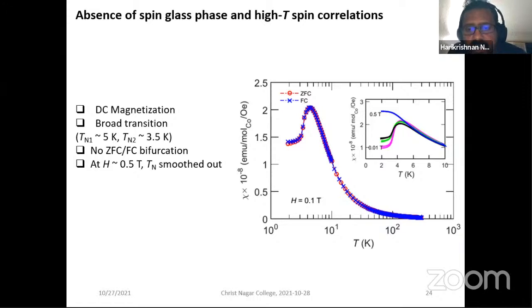Once you measure that, we see a very broad peak below 10 Kelvin. And then with the magnetic field, you see that the peak goes away and it slightly increases. So it means that there is a very broad transition. It could be long range ordered or short range ordered, meaning that it could be completely ordered or somewhere in between. But what we see is that it looks like there are two phase transitions, one at 3.5 Kelvin and one somewhere around 5 Kelvin. They are nearby, but they are all at low temperature.